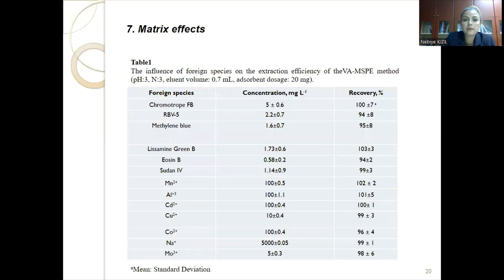Matrix effects. To evaluate selectivity of the method, some organic and inorganic ionic species like sodium, cadmium, methylene blue, eosin B were added to our sample solutions. We can see from table 1 that the method shows high selectivity in the matrix mediums.